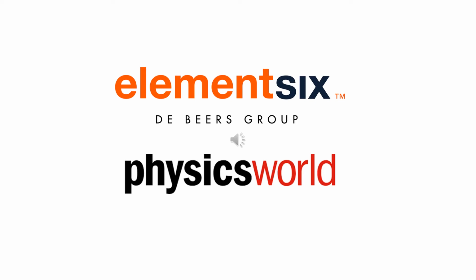So what does that mean? It means these electrons in these ground states get excited to optically excited states, and then they relax, come back down, and emit light. Unique to the electronic energy levels of this nitrogen vacancy center is that when the electrons come back down from their excited state, they preferentially drop into the ms=0 state, the ground state. So by shining green light on, we can spin polarize this nitrogen vacancy center. Effectively, we can drive all the electrons into the ground state. So, if you like, a spin temperature of 0 Kelvin, while the bulk crystal can still be at room temperature.